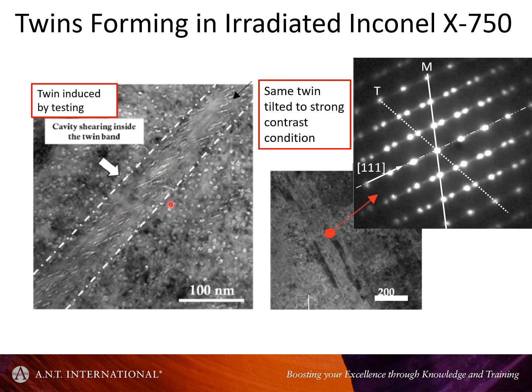When this twin is tilted so that we get stronger diffraction from it, and this is a lower magnification image of that volume, you see the characteristic twinning structures. So you can't tell what it is here. You have no idea what it is because you're in absorption contrast. You're not imaging anything with diffraction contrast, but here we have diffraction contrast, and this is where the twin reflections show up very strongly along with the matrix.